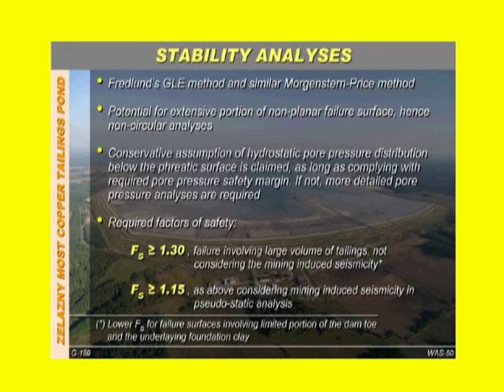The next, stability analysis. The stability analysis is currently done using the Fredlund global limit equilibrium method and the similar Morgenstern-Price method. There is a potential for an extensive portion of non-planar failure surface, hence non-circular analysis. This is mostly due to these glaciotectonic phenomena. We are always, except in some specific cases, making the conservative assumption of hydrostatic pore pressure distribution below the phreatic surface, as long as this very conservative assumption complies with the required pore pressure safety margin. If not, more detailed pore pressure analyses are required.